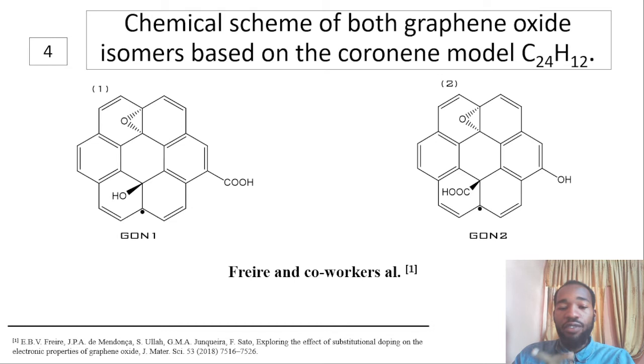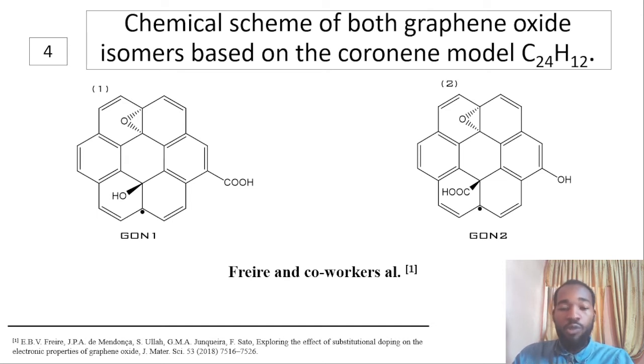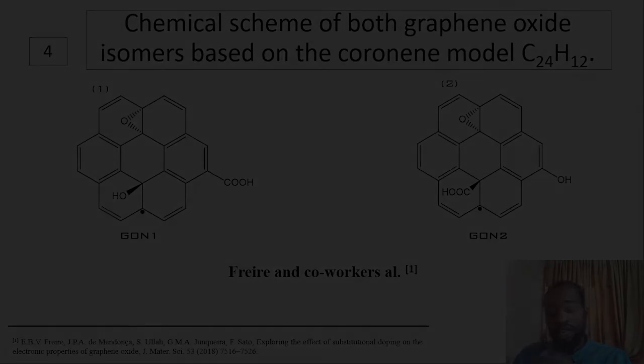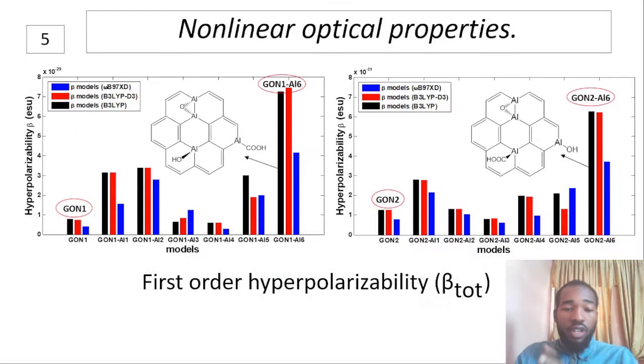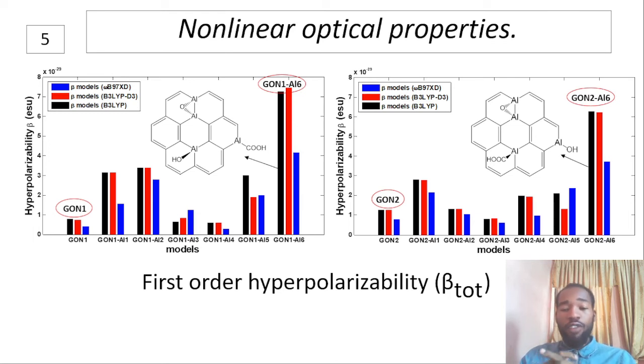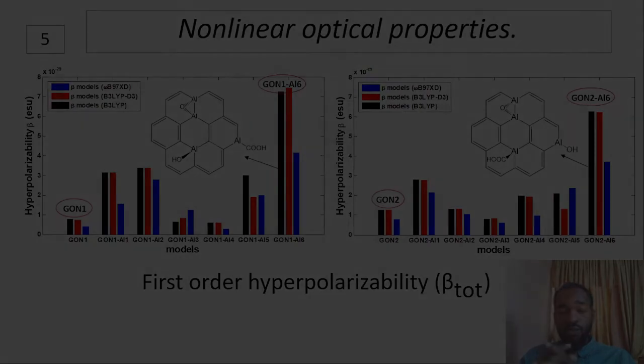It should be recalled that Freire and co-workers presented nitrogen atom as an effective doping agent of graphene oxide, as it significantly enhances electronic properties. Following their work, we propose to evaluate the impact of nitrogen atom doping on the optoelectronic linear and non-linear optical properties of graphene oxide nanosheets. The evaluation showed that the substitution of a carbon atom supporting the functional group within the system is very effective to drastically increase the first-order hyperpolarizability parameters.